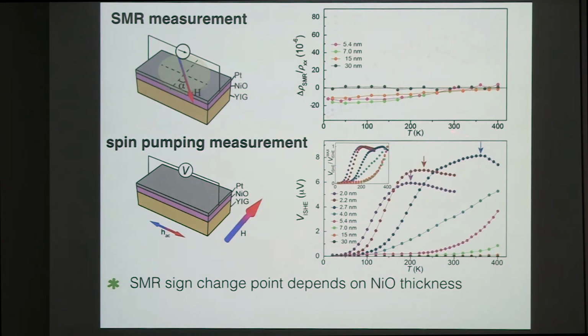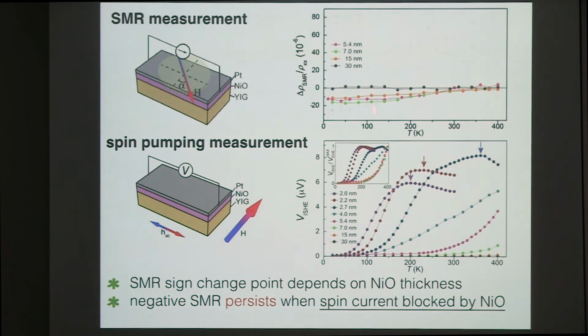But if you look at the relatively thick nickel oxide samples, and pay attention to this green curve, which is 7 nanometer, something is here, and the 15 and the 30 are even beneath it. Which means that for these three samples, the spin transmission, at least in the low temperature regime below 200 Kelvin, is 0. Nevertheless, you still have finite SMR, right? This clearly tells you that even if the thickness is over the value that can block any spin transmission, the SMR can still survive a little bit, but finally it goes to 0 at 30.